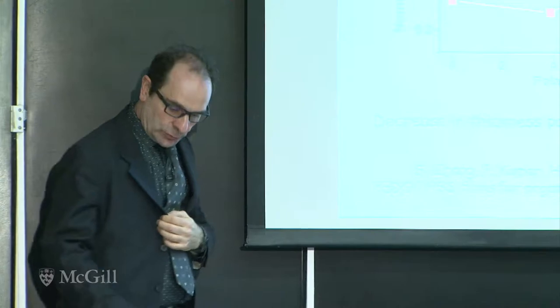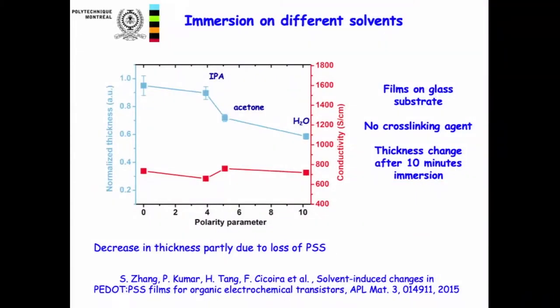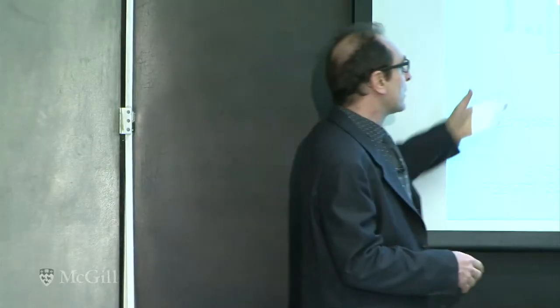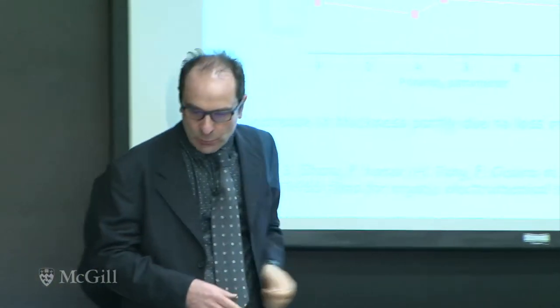This is an example of what can happen to your conducting polymer film. So we found this a few years ago. So if you make a film of this conducting polymer on a substrate, and then you soak the film in different solvents, you can have thickness decrease. So it means part of your film is dissolved, especially if you use a polar solvent such as water. So actually, this is something you don't want, especially if you work in biology. You don't want to lose part of your film because you immerse the film in water.